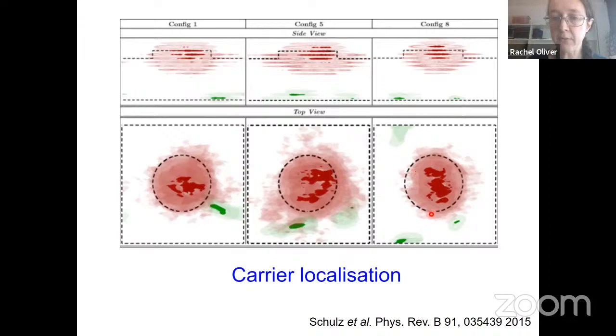Now, if we look at that overall, we've got both the electron and the hole trapped. They're trapped, in fact, separately from one another, which will have real consequences for the optical properties of the material. And in one case, there actually is a trapping at a compositional fluctuation, but it's not like a big cluster of indium, like the original suggestion. It's just a tiny little local random fluctuation in the indium. But together, the step and the little cluster of indium are enough to trap both the electron and the hole.